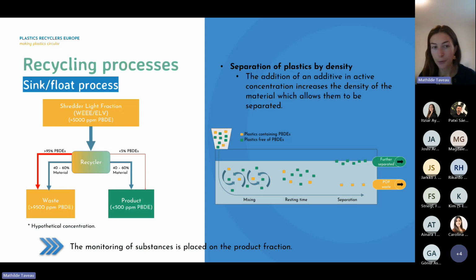What is done currently in the different recycling processes, and especially here if we take the example of electronic devices, so the waste from electrical and electronic equipment, and especially this shredder light fraction, which is the plastic fraction, but still contains, let's say, a lot of different impurities. This fraction is usually placed in a sink float bath. So this is a bath that has been set at a very specific density, and you have to know that the plastics that are contaminated with, for example, flame retardants, such as a brominated flame retardant, which contains heavy elements, and the bromine element is a heavy element.